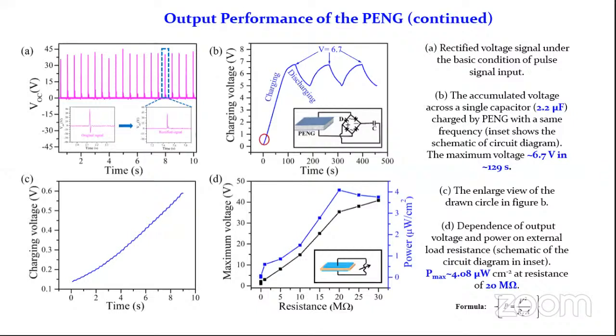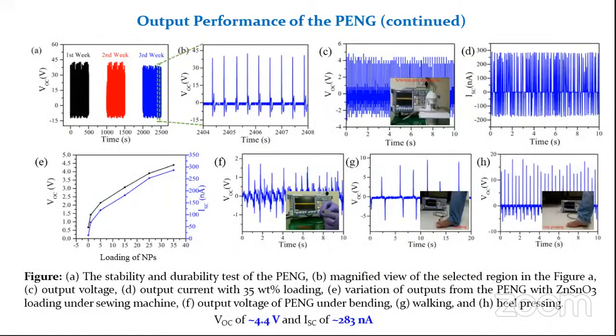We have also checked the output performance under various load resistance. We have seen that at 20 mega ohm of resistance, we have got the maximum output power of 4.08 microwatt per centimeter square. We have calculated the power using the formula V square by RLA. To check the durability of the fabricated PNG, we have tested the sample for 3 consecutive weeks. We have seen no change in output performance for the 3 weeks.